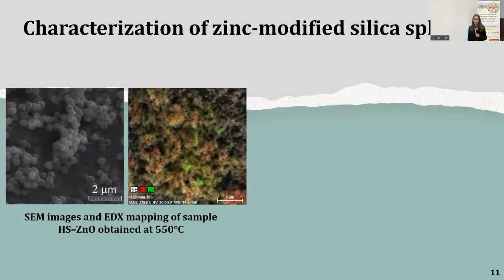These materials were analyzed by scanning electron microscopy, and the images suggest the zinc oxide is found inside the silica spheres, in agreement with diffraction data that proved the amorphous nature of nanoparticles. The zinc oxide distribution was evaluated by EDX mapping. As you can see with green in that image, there is a uniform distribution of zinc in the material.